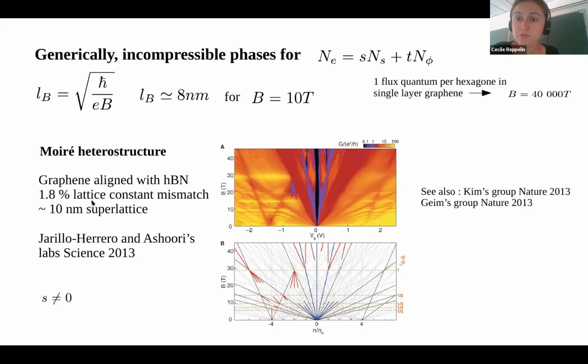So that will allow you to explore new things compared to your purely quantum Hall regime, and more specifically, it will allow you to explore the regime S non-zero in this Diophantine equation here. If I'm looking a little bit closer at the data, this is longitudinal conductance. Basically, I want to look at the darker colors here, which correspond to smaller longitudinal conductance, because that means I have an incompressible phase, and I will see lines in that case in the B versus electronic density plane. Here, the unit is the gate tension, which is what allows you to actually change that density in the sample.